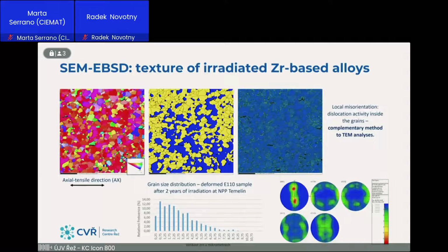Here are some results from electron backscatter diffraction that complete the TEM results in lower magnification. So we can observe the grain orientation as well as the grain texture, and the right image, the blue one, is full of local misorientation areas. So we can evaluate the density of dislocations which can be caused by neutron irradiation. So this is the local misorientation method, which completes the TEM results where we observe the dislocations in high magnification.